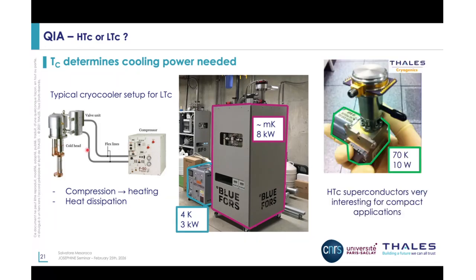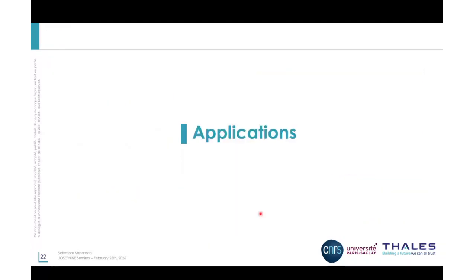But if we instead focus on high TC superconductors, then we can think about using these small, miniature, compact cryocoolers that actually fit in the palm of your hand. You can see here one example. This is a cryocooler developed by Thales Cryogenics, which is a division of Thales. It's a machine that is capable of cooling down to 70 Kelvin by consuming just 10 watts. And the time scale of this cooling down is about 2 minutes. So super fast, very low energy needed. The fact that we focus on high TC superconductors opens the way to many portable, embarkable applications, all sorts of applications where low TCs will not allow us to take this step towards applications. So let's talk about them.